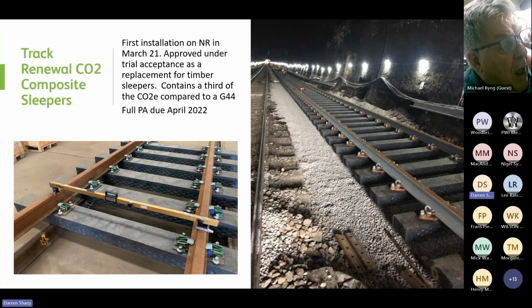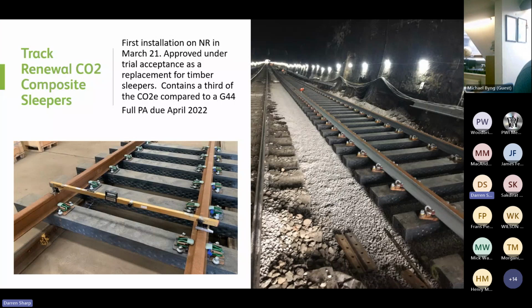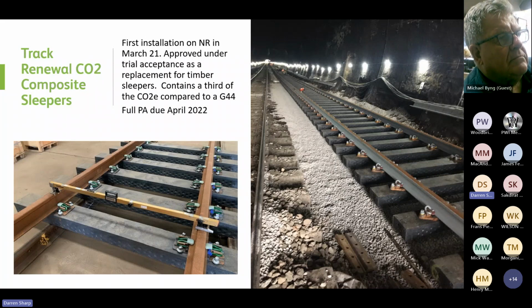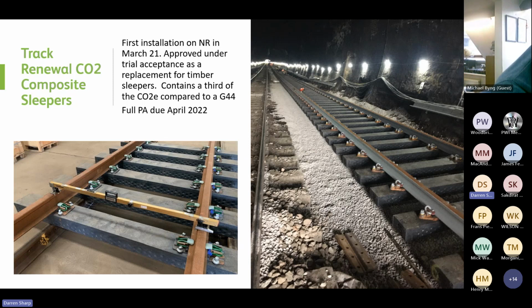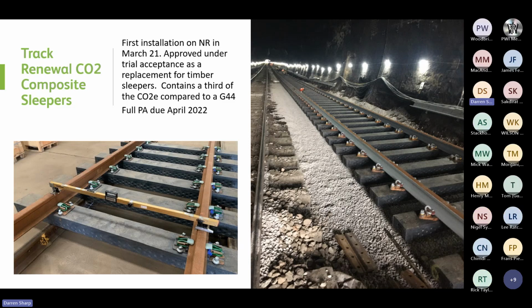One of the initiatives within the TA that was introduced in March 21 was composite sleepers. This is approved under trial acceptance as a replacement for timber sleepers that contains 1/3 of the CO2 compared to a G44. So full PA is actually now in place, and we're looking at full PA for higher speeds as well. At the moment, they're approved up to 100 miles an hour for Cat 1 track. And there's two various depths of them as well, 135 mil and 155 mil. Ideal for use in tunnels as well, where you've got smaller and more confined spaces where you need to short end and chamfer, and also on structures where you need a lighter sleeper because they're a similar weight to timber, 1/3 of the weight of concrete.